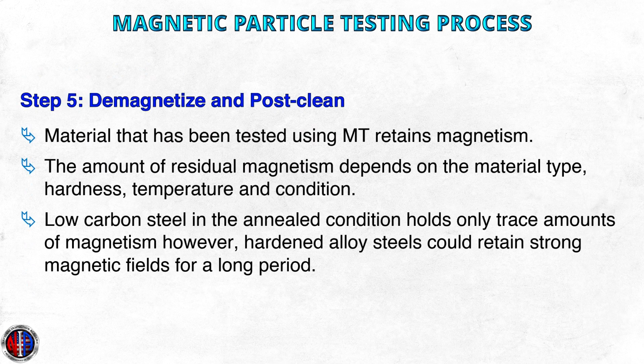Step 5. Demagnetize and post-clean. Material that has been tested using magnetic particle testing retains magnetism. The amount of residual magnetism depends on the material type, hardness, temperature, and condition. Low-carbon steel in the annealed condition, which is the most common, holds only trace amounts of magnetism. However, hardened alloy steels could retain strong magnetic fields for a long period. Typically, demagnetization of the test material is required after MT.